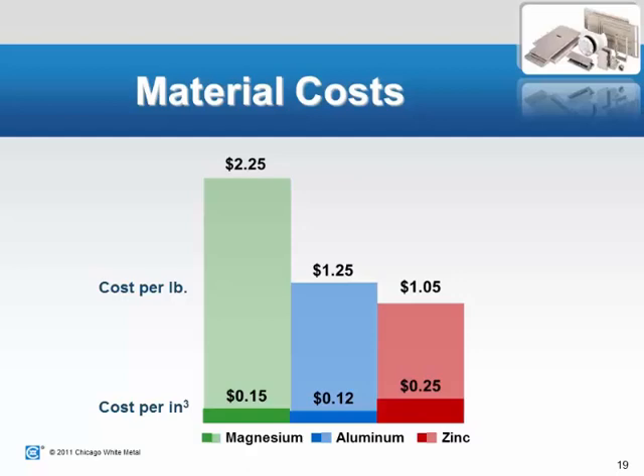And with the metal prices as they are right now, aluminum is slightly better than magnesium for cost per cubic inch, as you can see by the two bars, and then zinc is significantly higher cost per cubic inch because, as we mentioned, the weight of zinc is about 2.5 times that of aluminum. So there are things we try to do to factor that out. Like I mentioned, if we can design out some of the wall thicknesses to make them thinner, that will help with the zinc cost per cubic inch part of it.